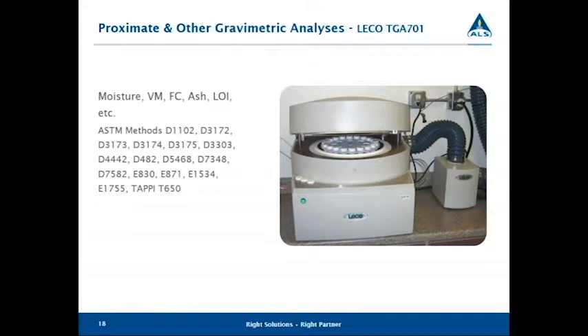Basically, it works on the principle of you have the small crucibles in there that we load up with 1 gram. The crucibles are pre-weighed by the instrument. We take the crucible out, add the sample, replace it back into the furnace. And there's actually a balance inside that furnace that will weigh each of those crucibles in a repetitive circulating motion. So each sample will be weighed maybe 100 times during one of the analytical processes.